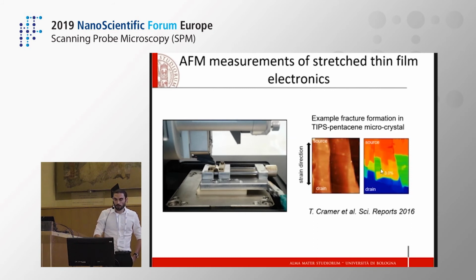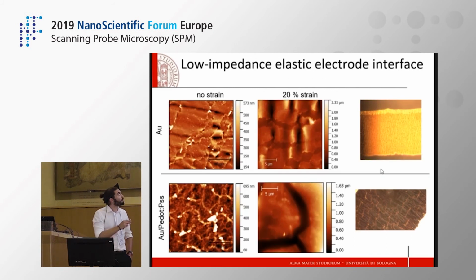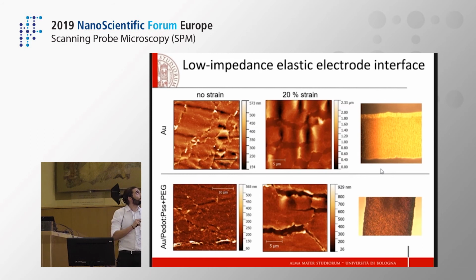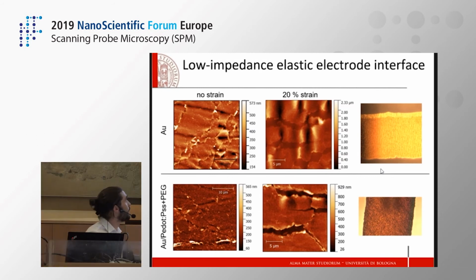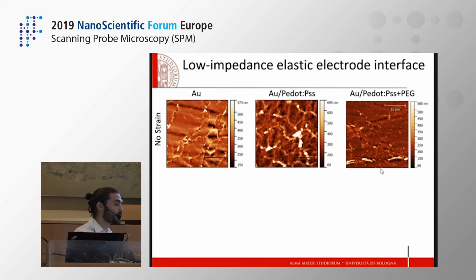And what we saw is basically that a comparison between gold and PEDOT:PSS shows that the micro-cracked pattern of gold is quite different from the huge cracks that form in the PEDOT:PSS coated one, seen both optically and also with AFM images. While the behavior of gold and PEDOT:PSS PEG is almost the same, with a micro-pattern of cracks. But how to understand this?